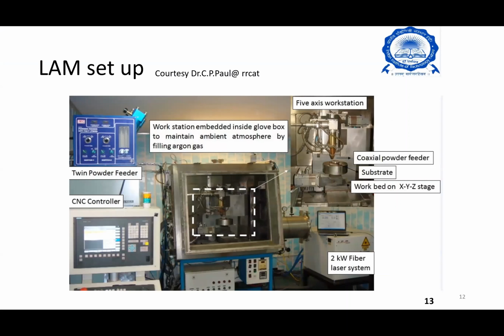So the laser beam was transferred to the 5-axis CNC laser workstation through an optical fiber and a quartz lens to focus the beam at the laser workstation. A defocused beam of diameter 2 mm was delivered at the substrate surface, and a pure titanium plate of size 100 mm by 100 mm by 10 mm thick was used as a substrate.